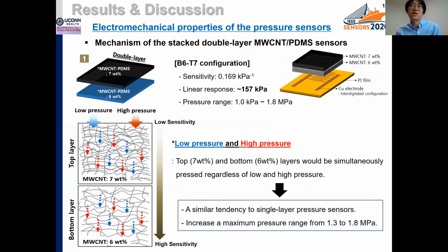This is the mechanism of stacked double layer composite sensors. In general, sensor performance strongly relies on a proper concentration of conductive fillers in elastomer-based composites. According to that, we focused on MWCNT concentration as the filler to investigate the mechanism of our sensors. As you can see in this slide, in the case of the B6 T7 double layer sensor, the top and bottom layers would be pressed simultaneously, regardless of low and high pressures. That's why the sensor shows a similar tendency to single layer pressure sensors.